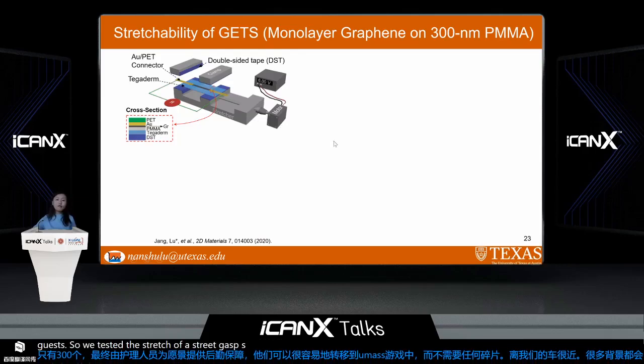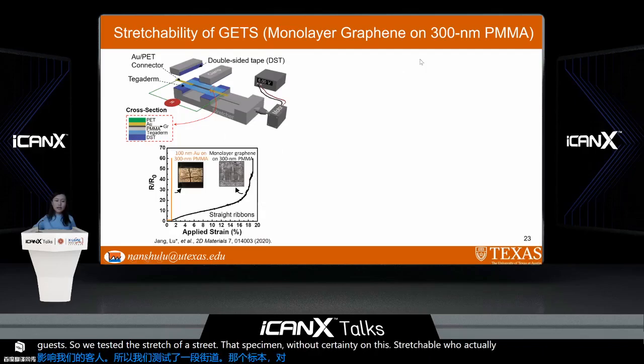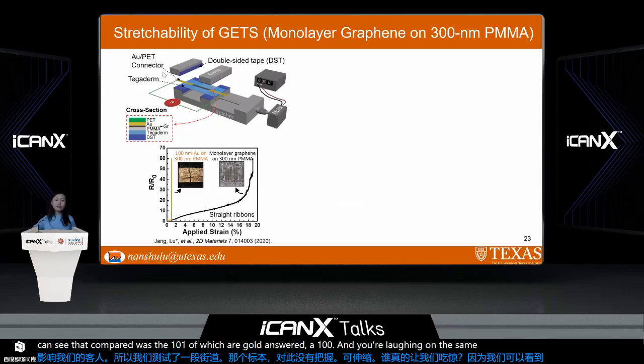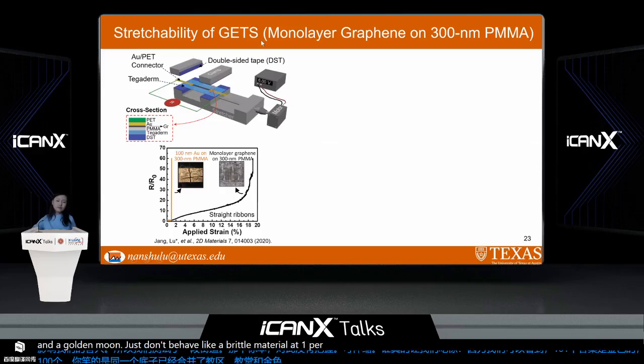This stretchability actually really surprised us because we can see that compared with the 100 nanometer gold on 300 nanometer PMMA, monolayer graphene on the same substrate has much better stretchability, and the gold just behaves like a brittle material, rupturing at 1%. So this kind of large stretchability, however, does not mean graphene did not rupture.